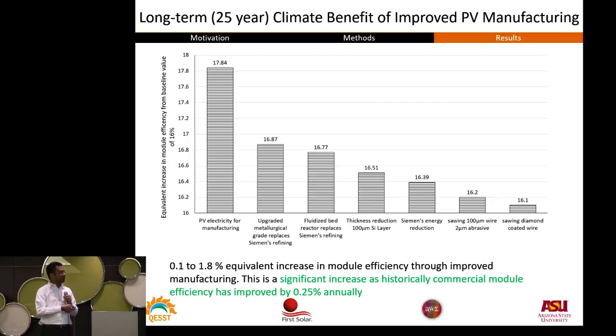This is important. 16% is the current commercial module efficiency, and you can get almost a 2% increase in efficiency on a life cycle basis. It might seem small, but actually it is significant, because historically, when the industry has expanded tremendously over the last 10 or 15 years, the average increase in module efficiency is just 0.25% if you do the calculations. So if you can get a 2% increase on a life cycle basis, it is significant.